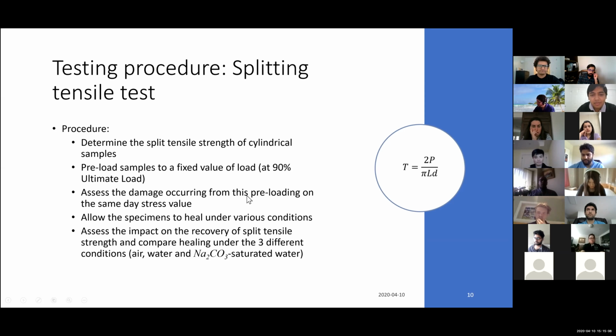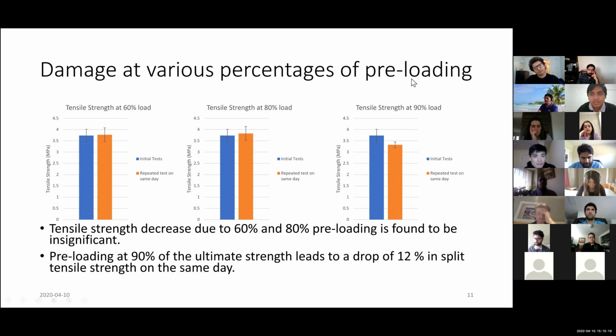And then I assessed the damage on the same day, and then allowed them to heal under different conditions, and then I tested them again. So this is what I did for selection of preloading level. You can see that first I tried at 60% of ultimate loading, and roughly there is no difference in these values. At 80% also there is no difference. It might be a slight increase, but there is a standard deviation here that contributes to it. So at 60 to 80% of preloading, in terms of split tensile behavior, it's not showing a damage.